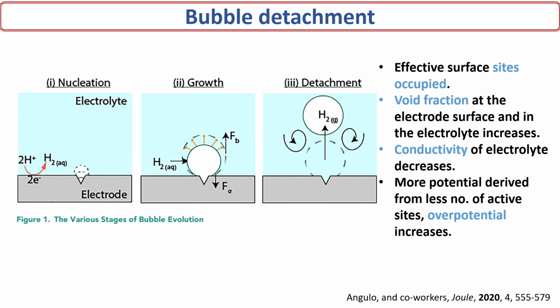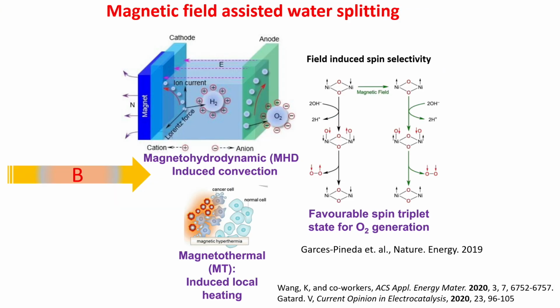People try magnetic field assisted water splitting, where there are two or three mechanisms. One is an indirect way, magnetohydrodynamic induced convection. By applying the magnetic field, the Lorentz force pushes the bubbles away and cleans the surface, thereby enhancing the activity.